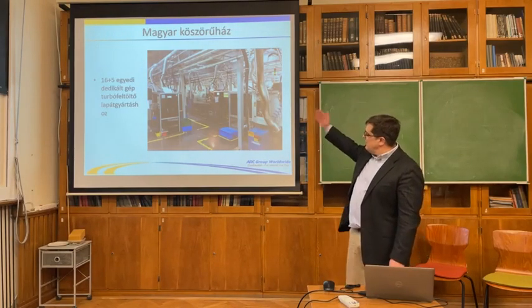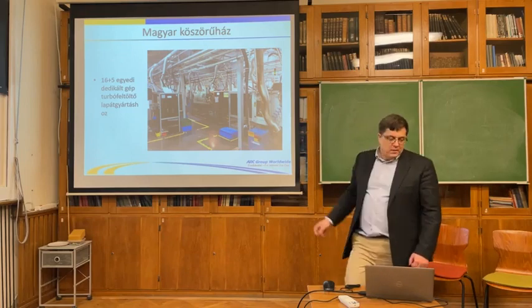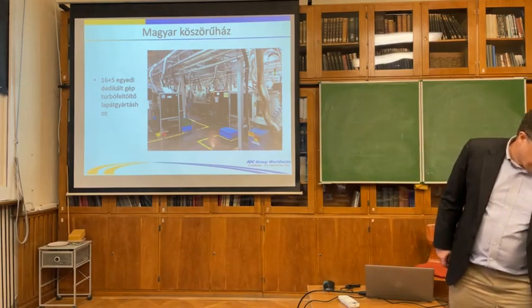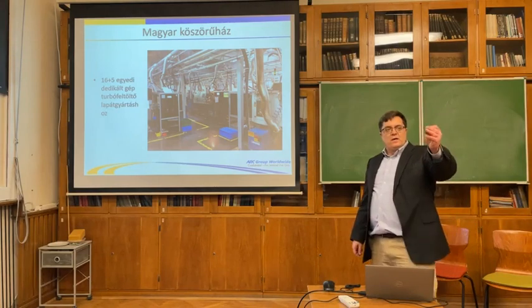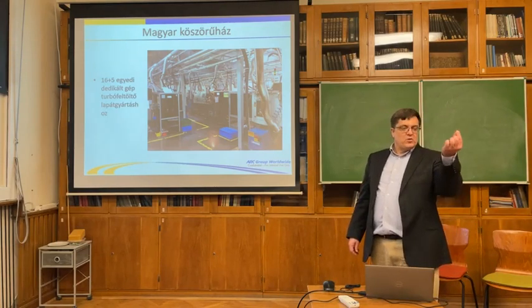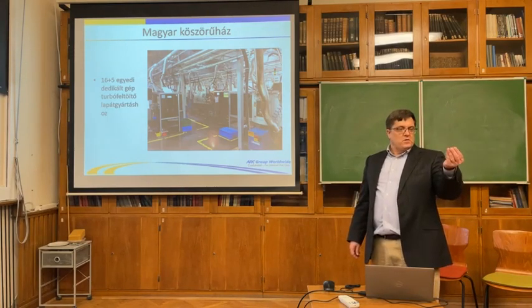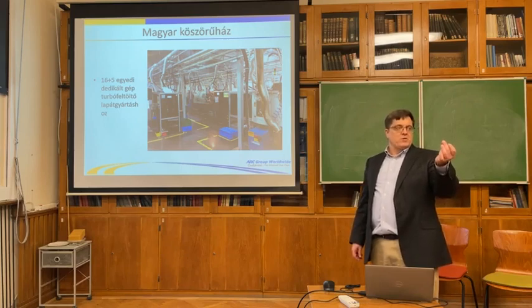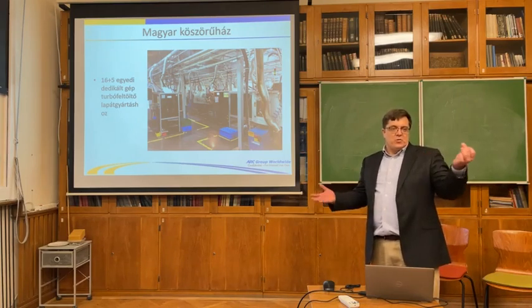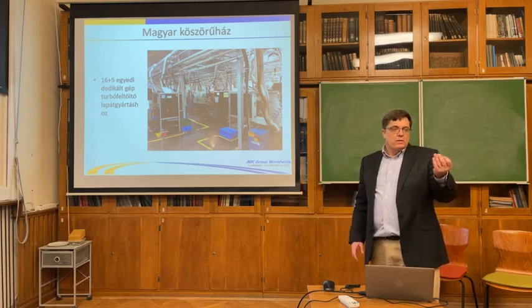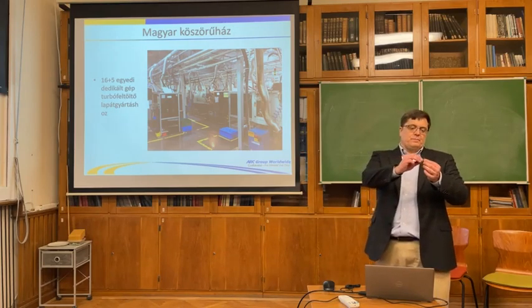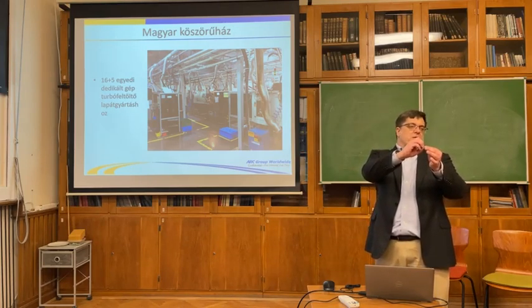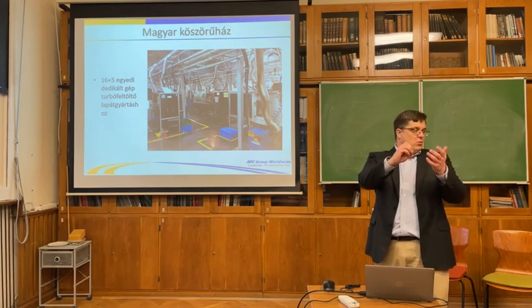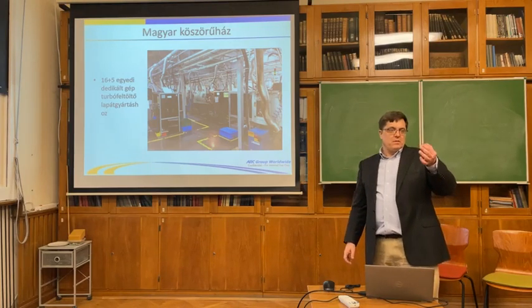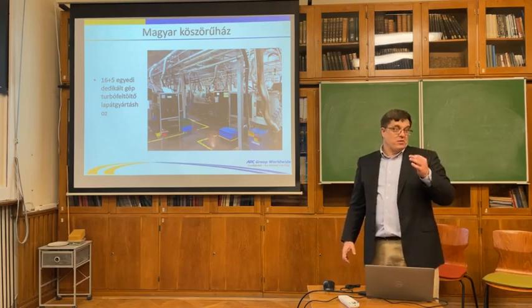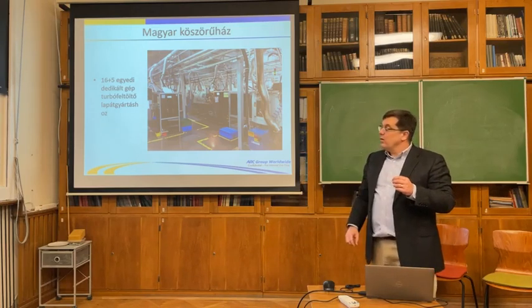So this one is our grind cell. And that's really important for all our turbochargers. This is a turbocharger vane. If you have a Volkswagen or Mercedes, they use the variable geometry turbochargers. What that does is it gets rid of turbo lag. You don't feel it anymore. But these diameters are done to plus or minus 7 microns, really tight tolerances. And this material goes up to 800 degrees centigrade, sometimes 1,000. So that's what these machines are for.